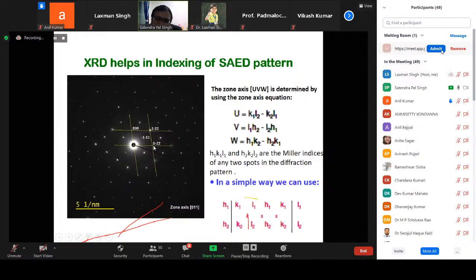As I mentioned earlier, electron diffraction is by nature centrosymmetric. So if this is the origin of the pattern, and this is 0 minus 2, then the other side will be its inversion. Just put a bar over the other side. So you can find one side and the other will be similarly determined. Now the most important thing is 200. How do you know that this is 200?